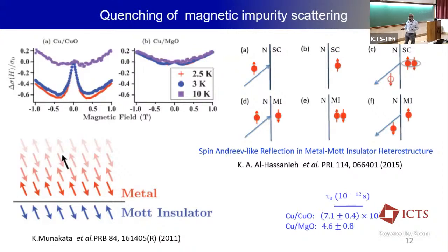The idea they postulated, because it was not really understood in 2011, was that when you bring a Mott insulator close to a metal, there would be an effect from proximity. We know that the proximity effect is very much revealed when you talk about a normal metal and a superconductor. But when you bring a Mott insulator to a metal, I do not think much will happen from proximity except some charge transfer. But what they surprisingly find is that there is an antiferromagnetic polarization that happens inside the metal, inside the copper. And there is an interaction going on between the impurity spins present in the material and the polarized spins.